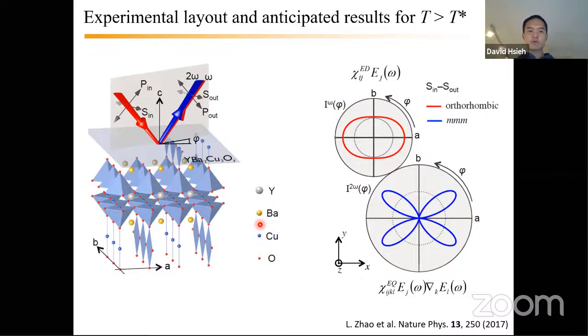Basically, we deploy the same layout that I talked about earlier, this RA type scheme. And we monitored both the linear and SHG channels. And I want to just talk about ideally what those patterns should look like if we refined our tensors under the reported orthorhombic mmm point group. Okay, so in the linear channel, at least in this S polarized in, S polarized out channel, S just means again that the electric field is perpendicular to the scattering plane of light.